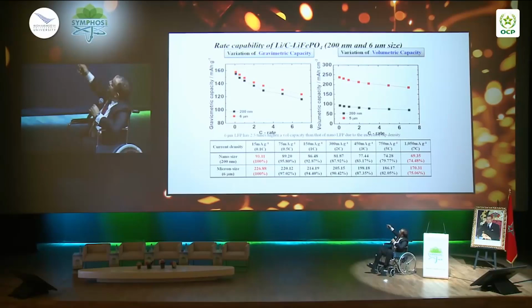And this is the volumetric capacity when you do fast charging and discharging. You can see clearly that the energy is much higher with the micron size iron phosphate versus the nano. And the power performance is very, very good. It's just parallel, basically. So we did not affect it. The bottom line is the performance is not affected because, as I mentioned, the lithium inside the particle doesn't have to go all the way out to the edge. It will just seek those pores, and then the pores are filled with the electrolyte, and the conductivity of lithium through the electrolyte is much faster than in a solid, where you have just a diffusion.